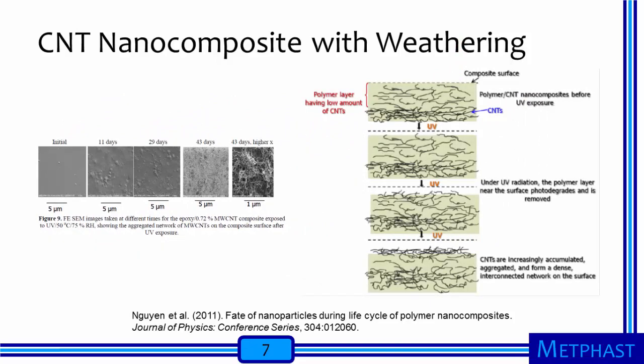This second image illustrates what happens during this accelerated aging. Initially, the nanotubes are fully embedded within the nanocomposite. The exposure to ultraviolet radiation breaks down the epoxy polymer, and the breakdown products leave in the gas phase. The carbon nanotubes are left behind, and as more of the polymer breaks down, more and more of the nanotubes are left at the surface of the weathered nanocomposite.